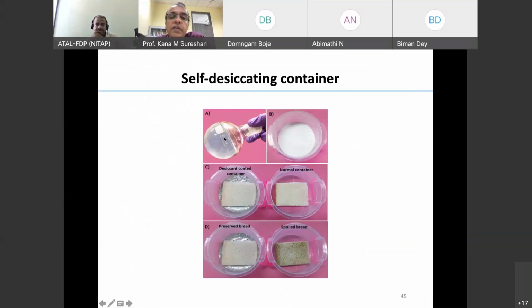Also, we have made a self-desiccating container using this gel. It's the same gel. We made the gel, put it in a container and polymerized it in the container. Now we have placed a bread piece. This is the control experiment. This is with polymer, closed and tightly sealed with Teflon. After a few days, you can see there is mildew or a fungal attack in the control, but there is no fungal attack here because it's desiccating. It's taking water. And to remove water, you don't need very high temperature. Just drying in air is enough. So this is a self-desiccating container made out of the gelator which we have made.